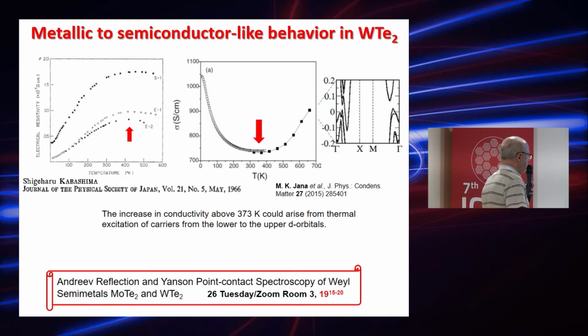We investigated both compounds using Andreev and Yanson point contact spectroscopy before, and this data will be presented in the poster the day after tomorrow. In this study, we concentrate on looking for the phase transition and such uncommon behavior of resistivity in these two compounds. We try to look for this transition also using point contacts.